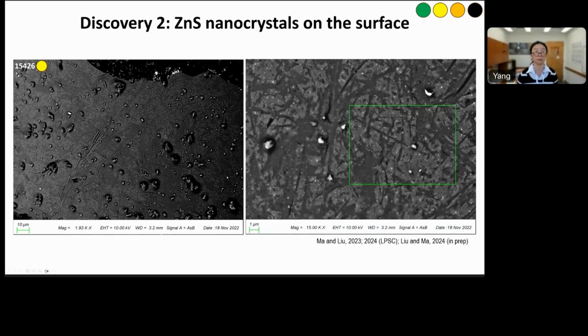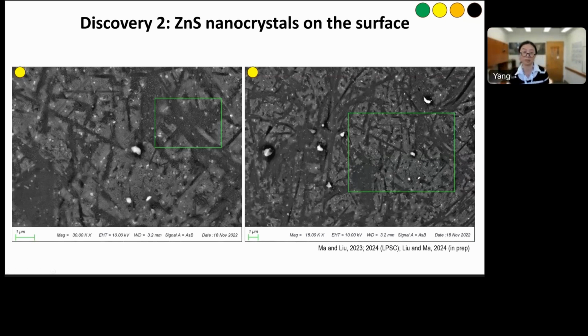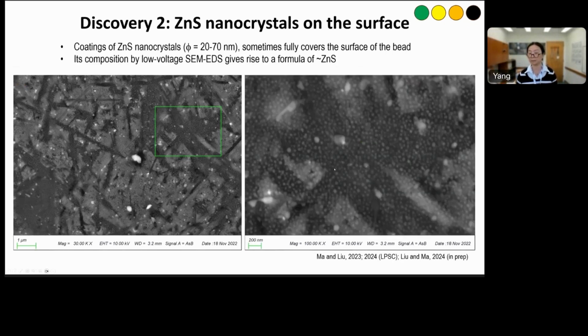The example shown was a yellow bead, but we have confirmed the zinc sulfide presence on 4 types of different beads. Here is an example of a zoomed out image of the surface of the bead, and zoom in. I borrowed this slide from Chu's presentation last year. As you can see, when we keep zooming in, we see the nanometer size zinc sulfide coating on this yellow bead. It seems to be a very uniform coating for this bead. The size ranges about 20 to 70 nanometers when we include all other bead observations.